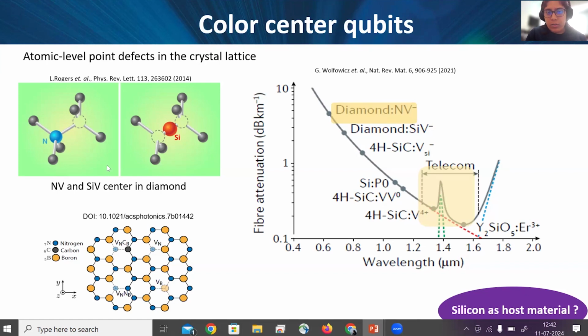Now, similar to that, there are other material platforms that you can use to have your point defects and color centers in them. On the right, you're seeing a comparison slide for different color centers coming from different host materials. And on the x-axis, it's the emission wavelength. So if you look at diamond or silicon carbide, you see that most of the color centers in these materials are emitting light outside the telecommunication band. The telecommunication band is something we desire to have our emission in because that's where the optical fiber losses are the least. So if you want long distance communication and send your signal from one point to another point, and the signal is in the telecom band, then you will have the least losses, and that's why it is desirable.